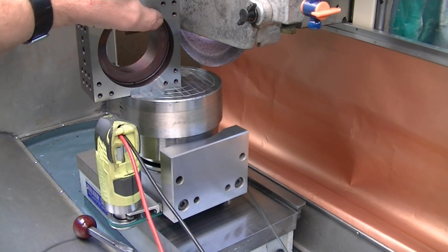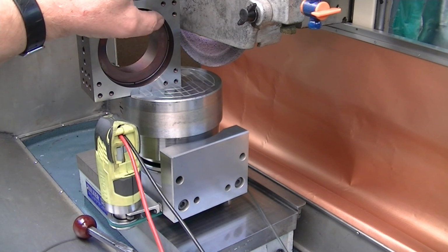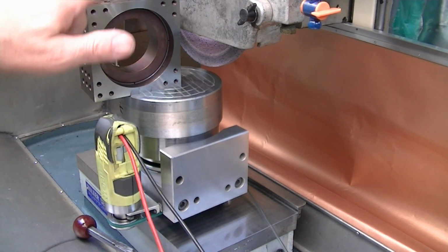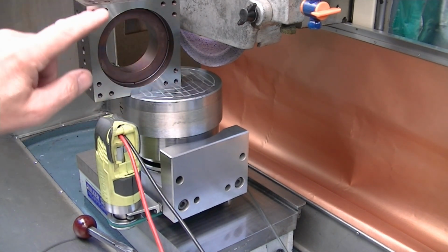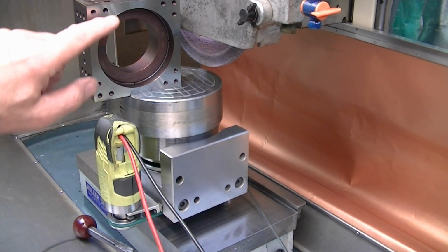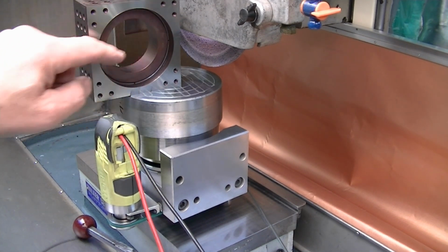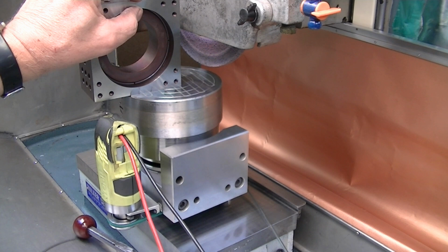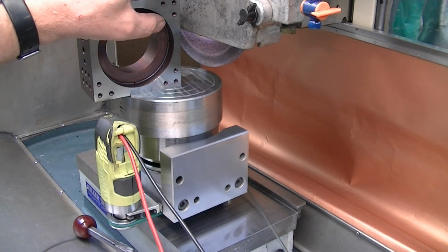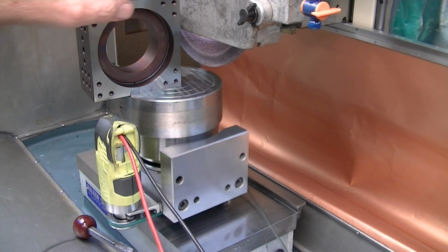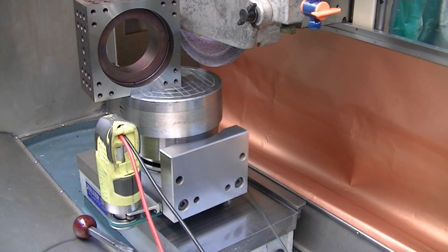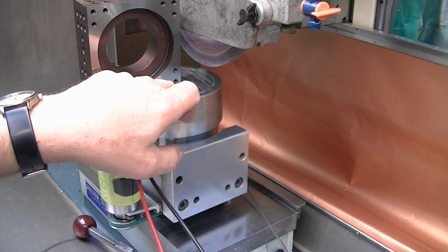But this minimizes the actual grind time, compared to traversing this and cutting air a lot, and also having vastly varying areas of engagement. Rotary, we have at least uniform engagement here and then out to this, so the amount of actual wheel in contact with the part goes way up when you're rotary grinding parts like this, or cylindrical parts. So that's the advantage of the rotary grinding.